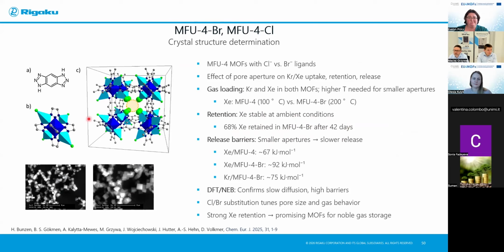This MOF consists of benzo-bis-triazolate ligands, and here you can also see the SBU of this MOF, which contains two types of zinc. One is octahedrally coordinated, and the other is tetrahedrally coordinated. And here on the right-hand side, you can see the unit cell with the pore aperture, and here are the halide ligands. In case of bromide, the diameter of the pore is smaller than in case of chloride.